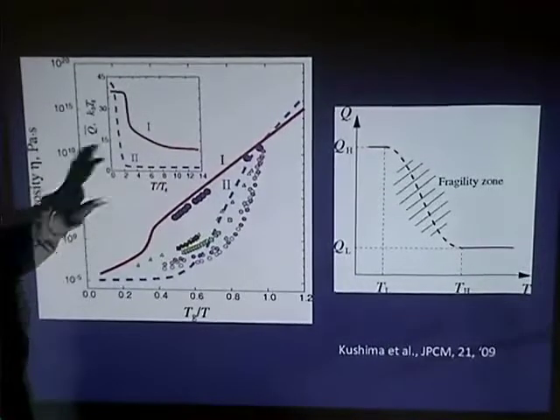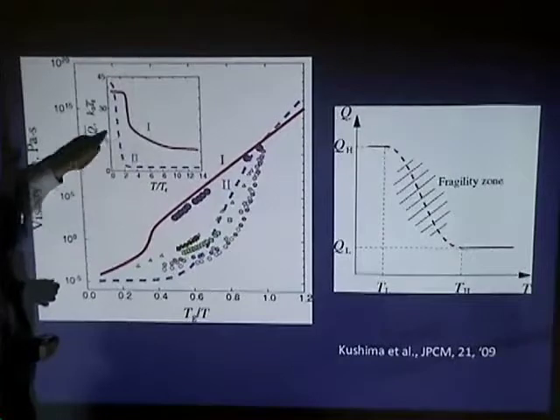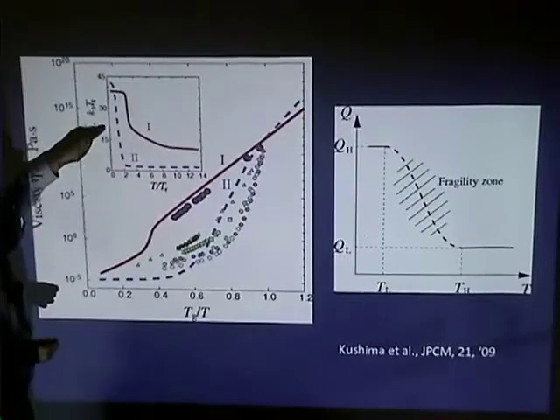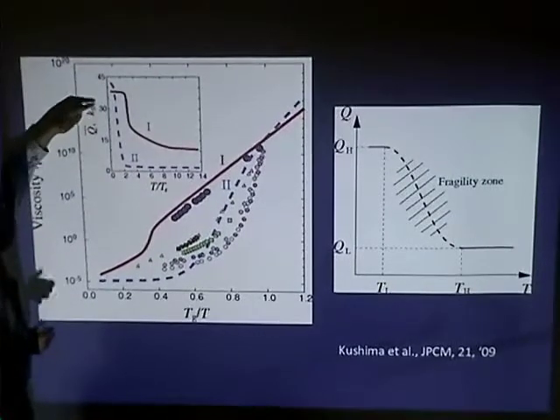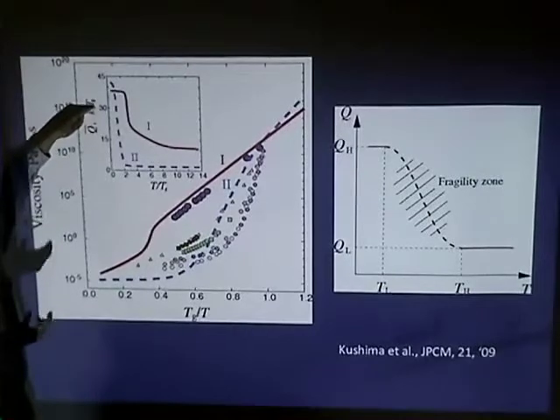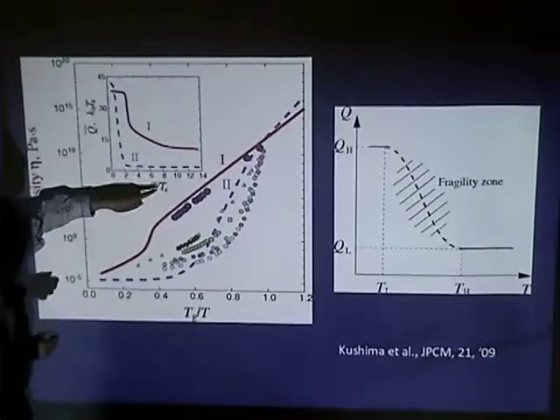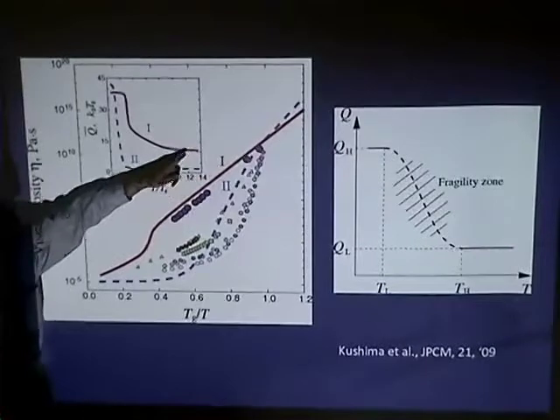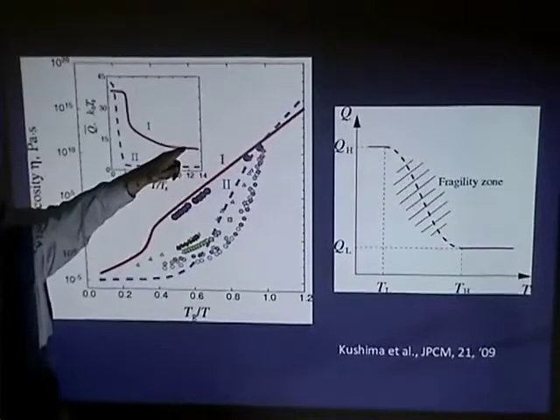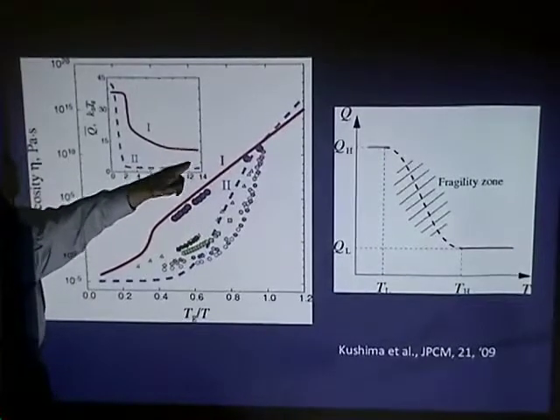No arbitrary parameter. So this is now activation barrier as a function of energy in units normalized to their own respective TGs. This is temperature. So you notice that at high temperature, silica and these glycerols are very different in terms of the required.